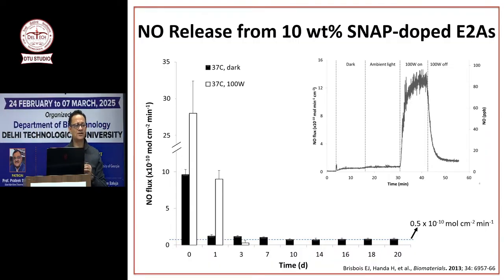So we have also made a nitric oxide releasing SNAP catheter that can be implanted, but has a fiber optic cable that you can insert inside this catheter. Because the fiber optic will release light, that light will trigger more nitric oxide release. So you can have that fiber optic going on for a few minutes or a few hours, or you can even have a short fiber optic, because a lot of the time the ports that you are using can get infected. You can have a port connected with the fiber optic. After you take the blood out or infuse something, put this cap on with fiber optic so that it can release more nitric oxide and take care of infection, if there was any infection, at higher levels. With this SNAP method, we were able to prolong the release to 20 days.